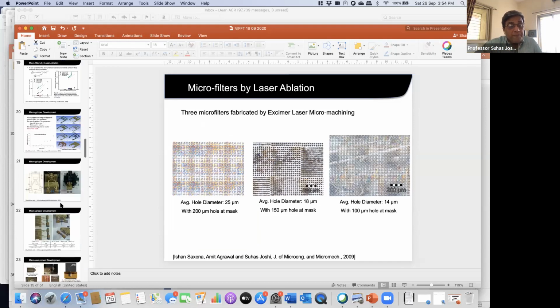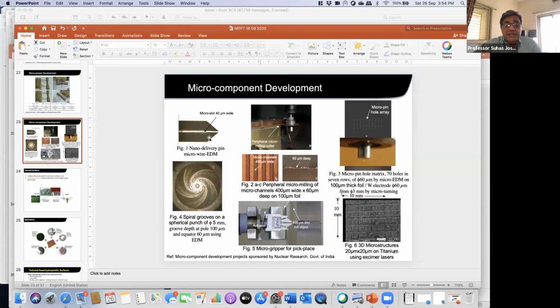Suppose if you take here, the sizes are like 40 micrometer size, over the entire length of say 10 millimeter. Here the width of the cutter is 400 micrometers, and 60 micrometer depth. This dimension is something like a 60 micrometer rod made from a 3 millimeter rod initially by turning. And then we use in situ EDM to make these 70 holes of 60 micrometers. The EDM process we use to make all those 70 holes.